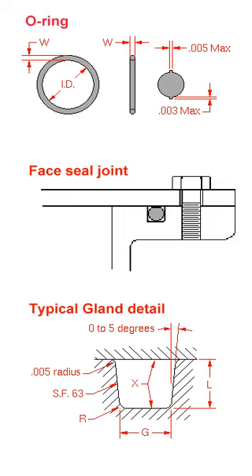In vacuum applications, the permeability of the material renders the point contacts unusable. Instead, higher mounting forces are used and the ring fills the whole groove. Round backup rings are used to save the ring from excessive deformation. High vacuum systems below 10^-9 Torr use copper or nickel O-rings. Vacuum systems that have to be immersed in liquid nitrogen use indium O-rings, because rubber becomes hard and brittle at low temperatures.